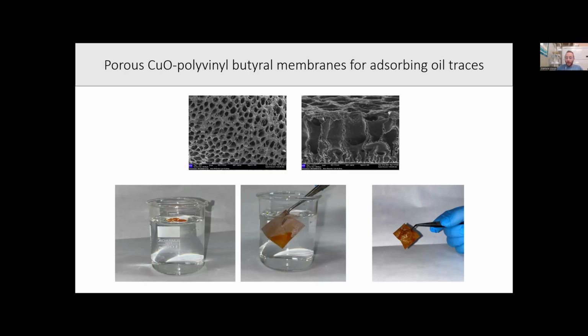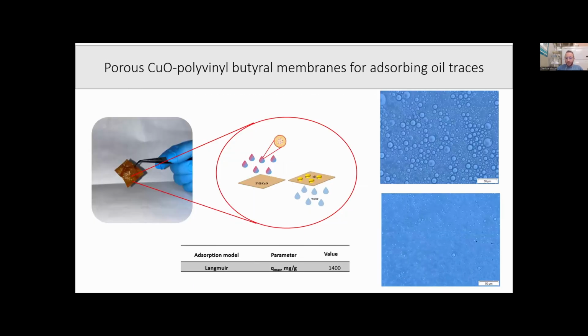In this case, we applied this membrane for adsorbing oil traces from emulsion, so from oil-water solution. Even in this case, different kinds of parameters were changed. You can observe on the right side the optical images before and after the adsorption. So the typical emulsion drops can be completely removed after the application of the PVB copper oxide doped membrane. So this membrane is able to selectively adsorb oil, proving the ability to separate oil from water. The maximum adsorption capacity is about 1,400 milligram per gram, proved by the application of a Langmuir model.